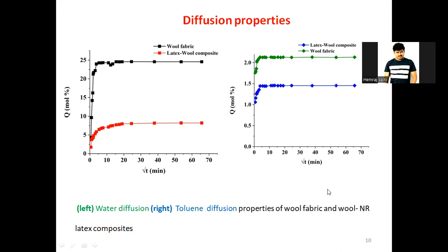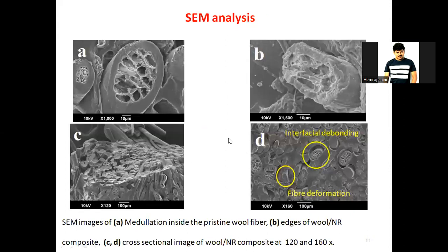This is the trend, and the difference between the latex wool composite and wool fabric in the case of toluene diffusion is minimal. Now this is the SEM analysis. In the SEM analysis you can see, first one, the medullation inside the pristine wool fiber. Medullation means there is a hollow space inside the wool fiber. This is known as medullation. So we have taken a medullated fiber only, and you can see the hollow space inside this wool fiber.